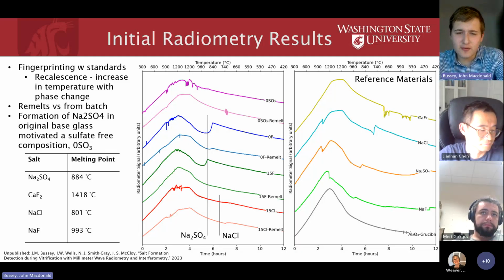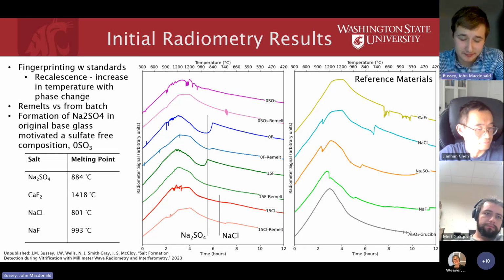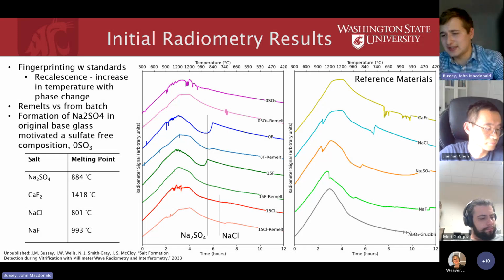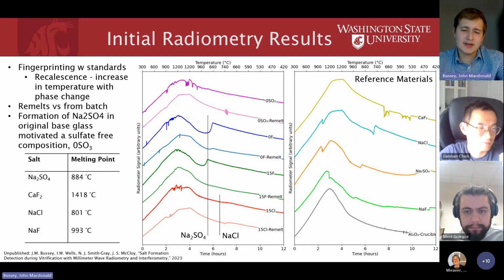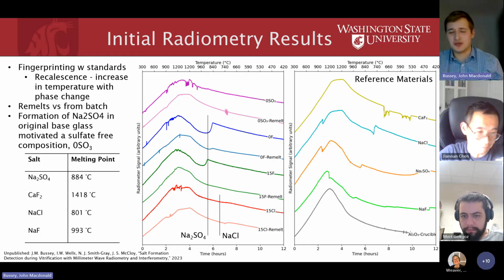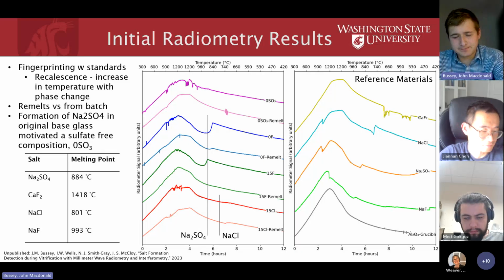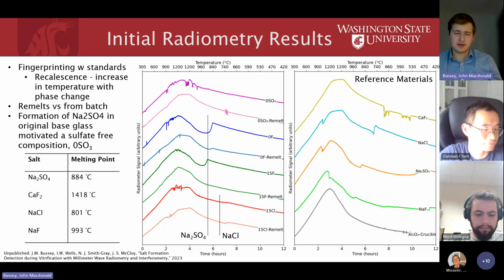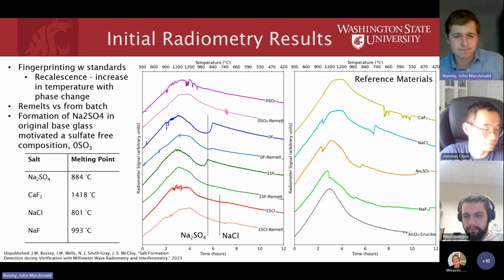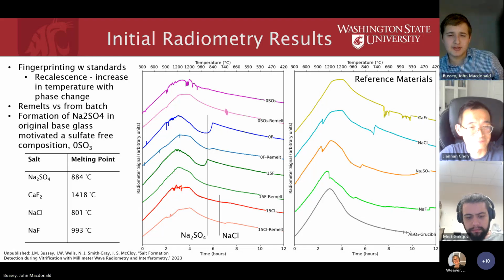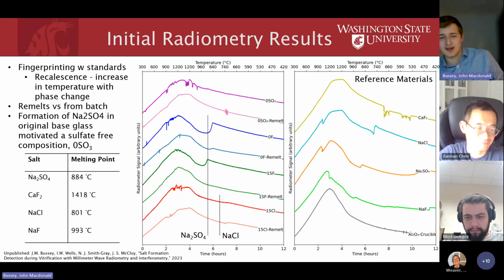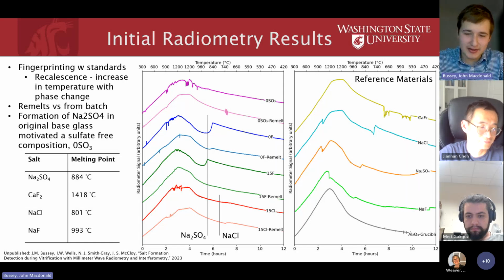And so we see that the salts form both in the sodium sulfate and the sodium chloride form at a fairly significant undercooling, which again we'd expect to be undercooled by 50 or so degrees, which is what we see here. And one other thing to note is that the sulfate detected in the fluoride glass is much higher, and so this maybe suggests there's some sodium fluoride, sodium sulfate binary that's forming, that's causing it to shift to higher temperatures for freezing.